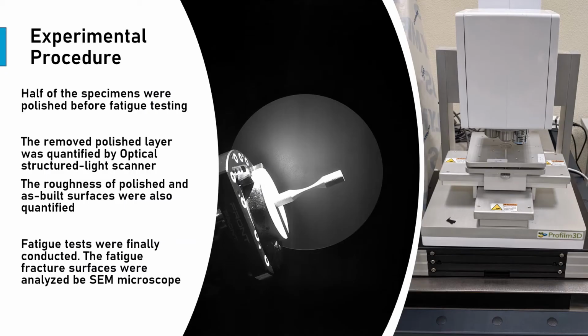Now, as experimental procedure, all specimens were analyzed in a 3D scanner before and after polish treatment. Only half of the specimens were polished, and after the polish they were again subjected to 3D scanning. We also used techniques to measure the roughness before and after polish treatment, and afterwards, after the fatigue tests, all surfaces were analyzed by the same microscope.